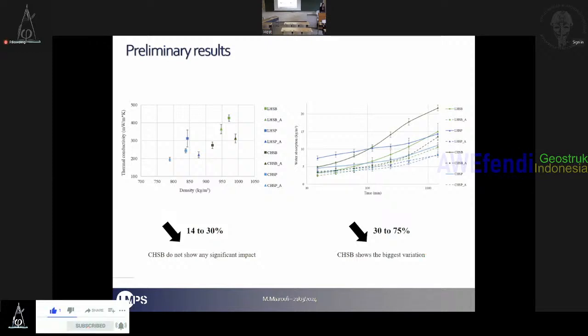Regarding the water absorption, we can see that all concretes exhibit the same tendency. Even the combination of cement and the large-sized chives, which actually shows the biggest variation after the aging. It's the green one. So, as I was saying, all concretes exhibit a decrease in the water absorption coefficient, and this decrease is actually a good thing because water absorption is a good indicator of durability. The higher it is, the lesser the durability is. The decreases can go up to 75% for the CHSB formulation.